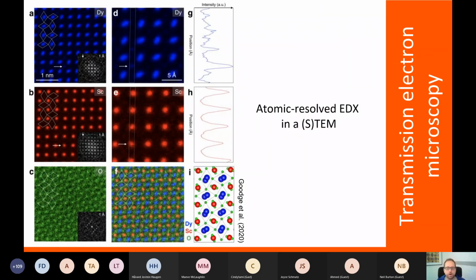And you can not only do this at a resolution of several microns, you can actually take this to atomic resolution and do atomic energy dispersive X-ray mapping using a scanning transmission electron microscope. This is a recent example here. You see the resolution now. We have a scale bar of 1 nanometer, and they map out individual atom columns using EDX. This is something we will look at in later workshops of how this could be done. But again, I wanted to show you that you can take EDX and element contrast mapping all the way down to atomic resolutions.